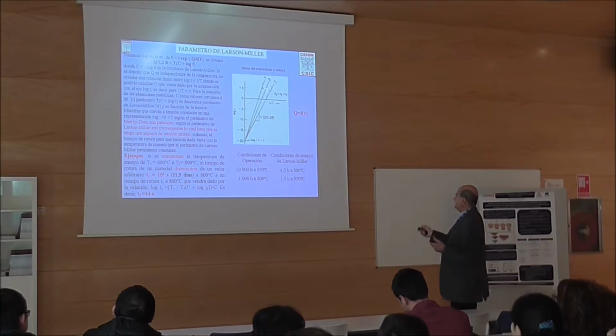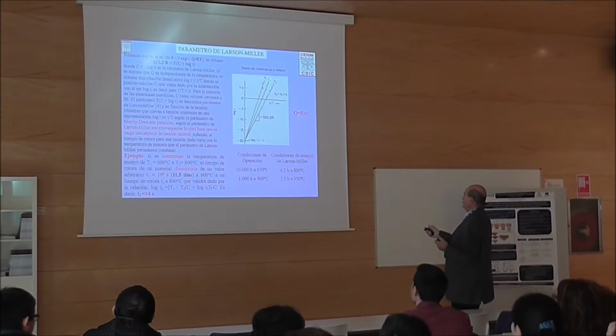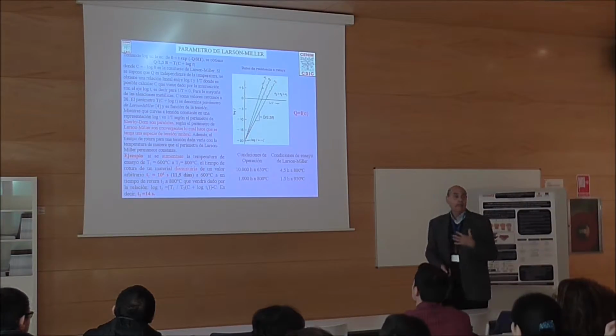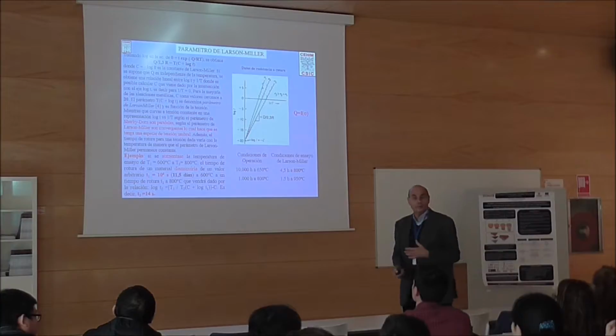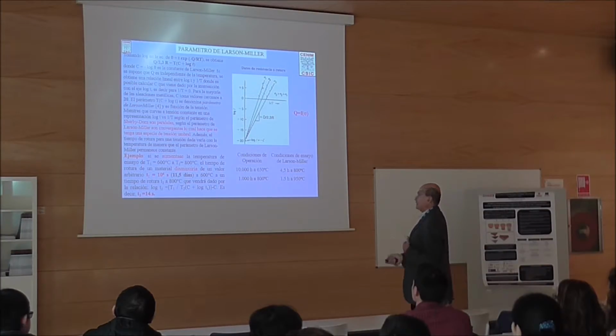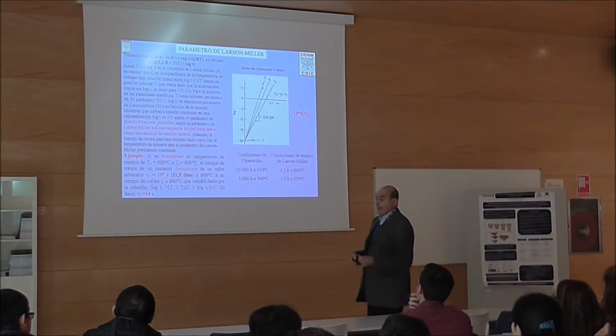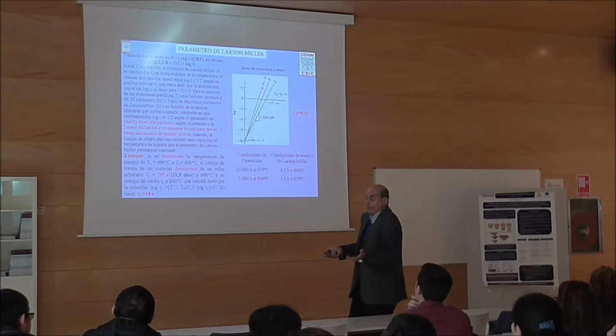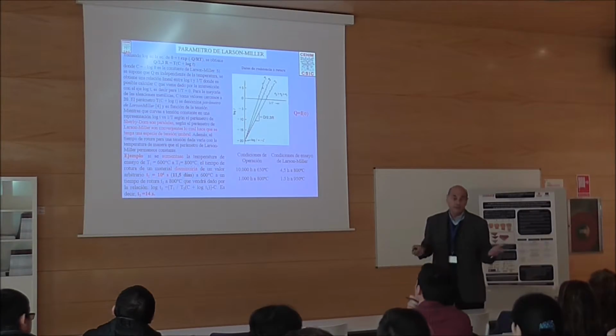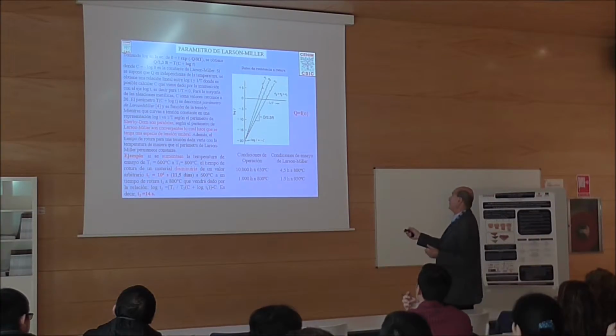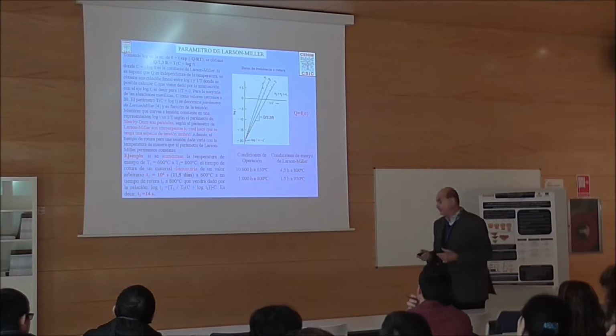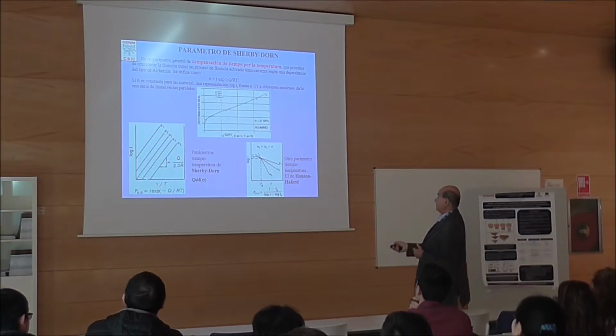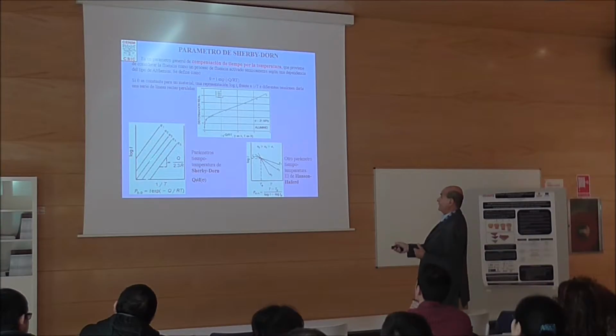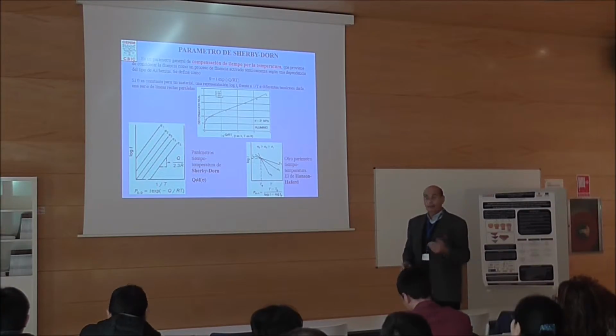You see that this is proportional to strain rate, this is proportional, and this is for different stress. You see that curves are not parallel. I believe in parallel curves, not in these convergent curves. But again, the life for the components is used by the engineers. The engineer doesn't understand mechanisms, they don't care about mechanisms, it's like a black box. So you put these constants in. I like much more, of course, the Sherby-Dorn, which are parallel, which has a physical meaning that I will